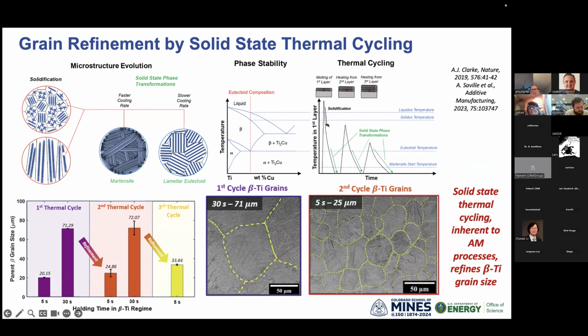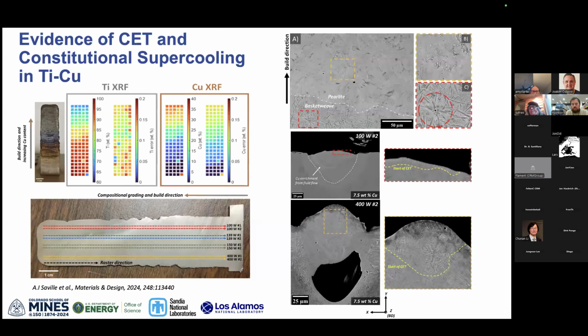And then what happens as you thermally cycle relative to the eutectoid transformation temperature? We did some controlled dilatometric heat treatments where we were cycling relative to that temperature, and we showed that we were able to refine and reset the microstructure and create refined grains just from solid state thermal cycling. So what's neat about this is it gives you another pathway, in addition to solidification, to refine the microstructure.